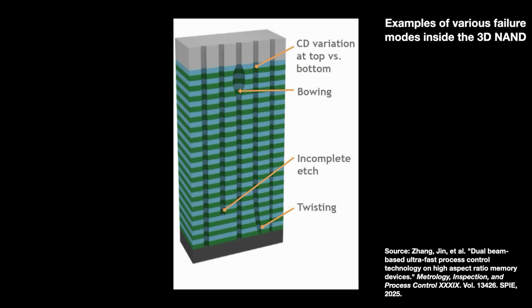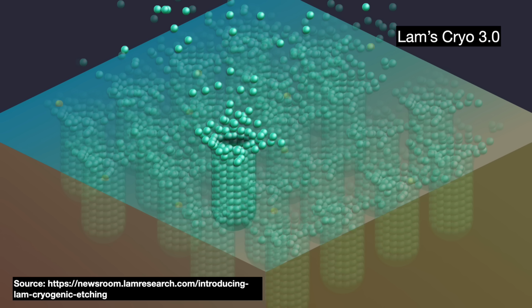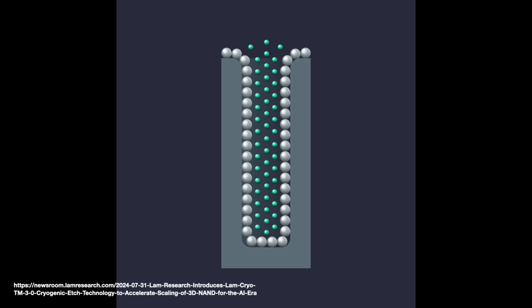Modern 3D NAND might feature memory holes 100 nanometers wide and 10 micrometers deep, a very high 100:1 aspect ratio. Existing methods do not work well, leaving issues like bowing, incomplete etches, twisting, or whatnot. So they developed cryogenic etching, a new type of etching done at cryogenic temperatures of -70 degrees or lower. Companies have been researching this since the 1980s, but it only recently reached the market due to the growing needs of 3D NAND. The need for very cold temperatures was one of the major issues for fabs to overcome.